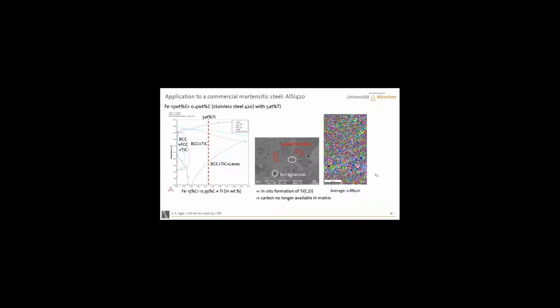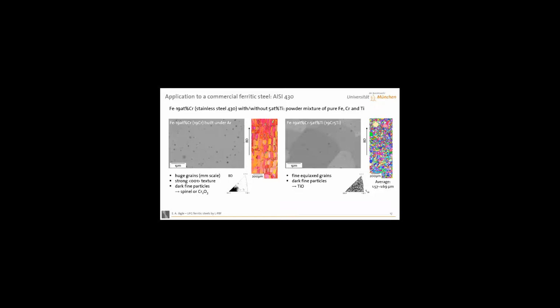We tried it out. We did get a lot of grain refinement. The problem is that probably a lot of the carbon is now bound in carbides if we add so much titanium. So we thought comparing this before and after addition of Ti is probably comparing apples and oranges. So we went back to our very boring model alloys. Well, you could say it's a commercial ferritic stainless steel, but in fact, it's just a binary iron 19% chromium alloy.